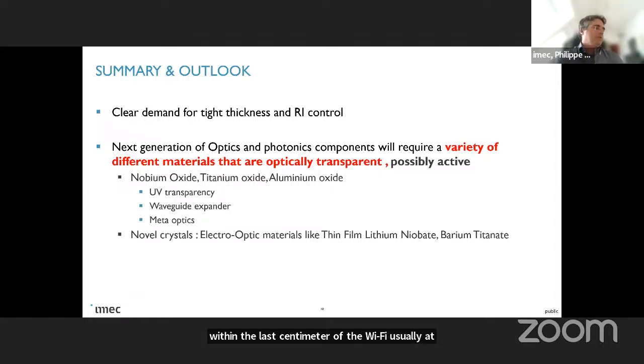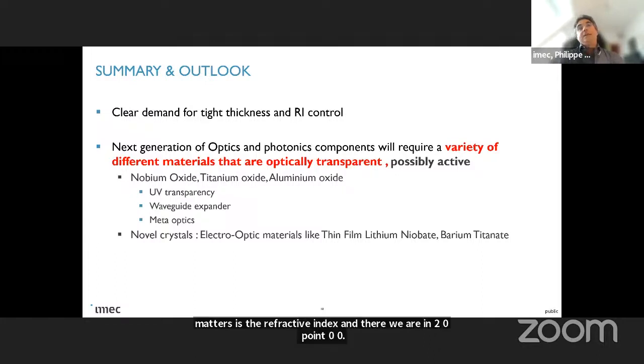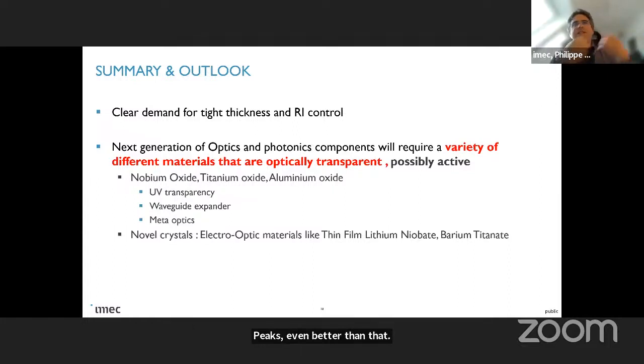Which is also very important for us is the refractive index control. Some people don't always mention that, but having a very uniform control is nice for the thickness, but actually what matters is the refractive index, and there we are into 0.00x, even better than that. That is extremely important. So for instance, when you're forming thin films and there is slightly different microstructure, a bit more of crystalline phase or a bit more of an orientation, we will be, quote unquote, seeing that in the performance of the devices. And that is something we are watching very carefully.